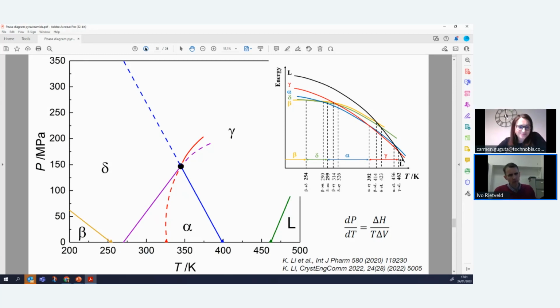Well, all the phase transitions we have monitored in the DSC on a constant basis, and actually at room temperature, if you have a pyrazinamide form, either beta or delta or alpha, it would barely convert. As I said, gamma does, because it is really a high temperature form, but in certain cases it also did.